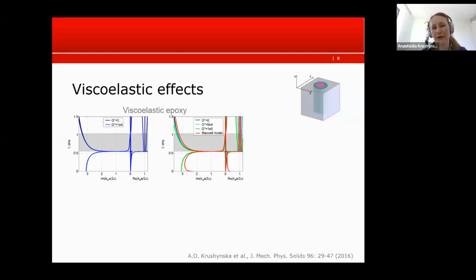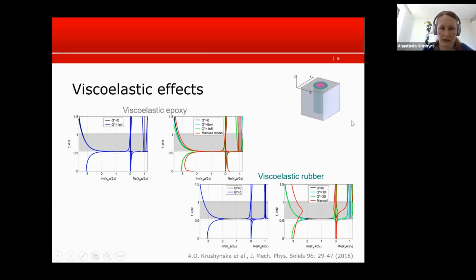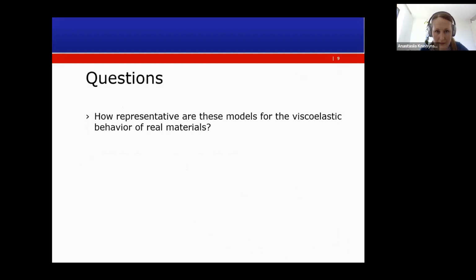Okay, I see. The number of terms in the generalized Maxwell model can be very different. In this work, we analyzed the behavior of viscoelastic epoxy and rubber. The Maxwell model was also fitting experimentally measured data, but these data were taken from other works, so I have nothing to do with those measurements. For epoxy, it was a 17 parameter model, if I remember correctly, so around that number. For rubber, it was 20 something elements, but it's not very critical, because the idea is that we need to have a good fit in the required frequency range, and more or less good agreement in the glassy and rubbery ranges.